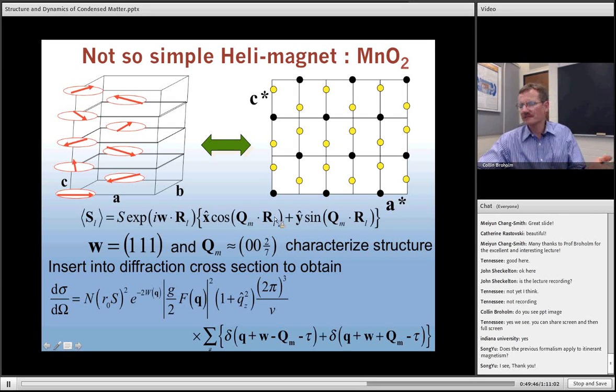If you evaluate this expression, it will generate this type of configuration. This factor here is actually implementing the way that the phase changes for this spiraling configuration when I move between different sites of this Bravais lattice with a basis. So that's why I need this factor to show up as well. And you'll get to explore and enjoy that in the homework problem. But fundamentally, it's this cosine term in quadrature which is producing the spiraling spin configuration.